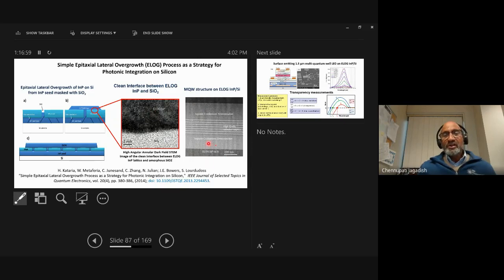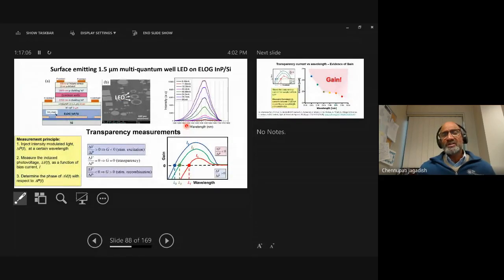And they're able to show that you can really get good quality quantum wells as well. Using this particular technology, it's a very complex growth process. It's a non-trivial process, and you need to spend a lot of time. Professor Sebastian Lourdudoss has been working in this area for about 20 years or so. Then they were able to demonstrate 1.5 micron multi-quantum well LEDs, not lasers yet, but they are LEDs.